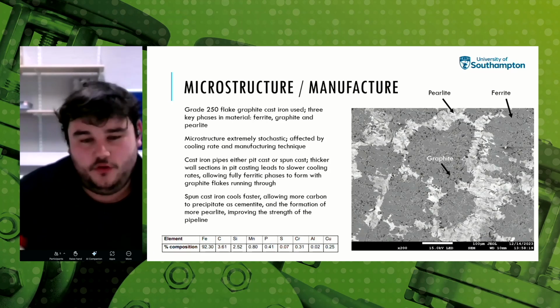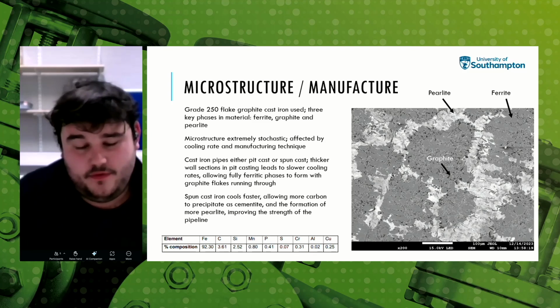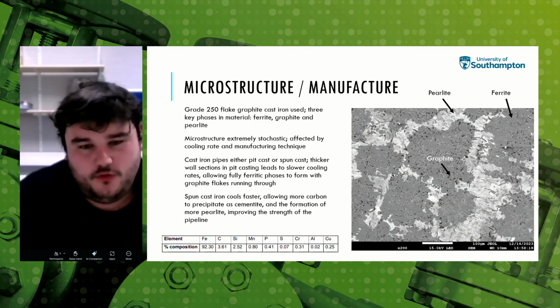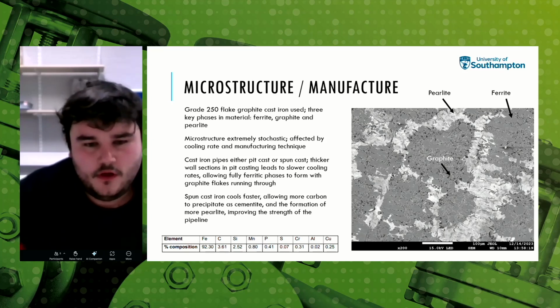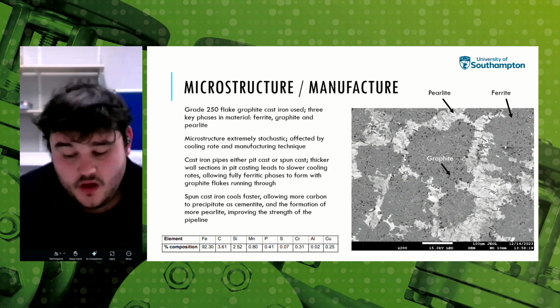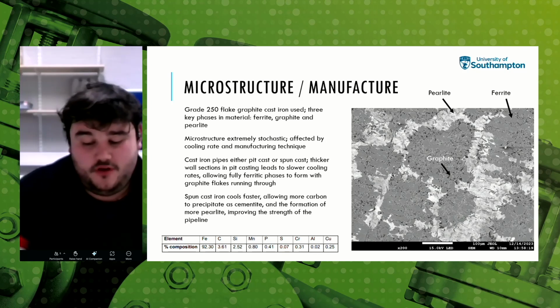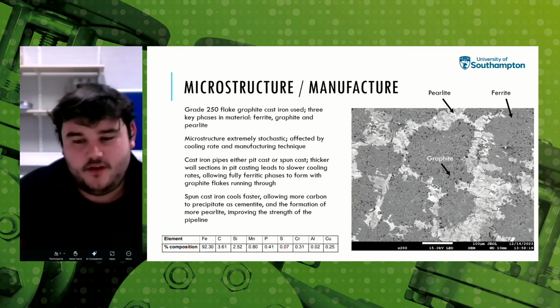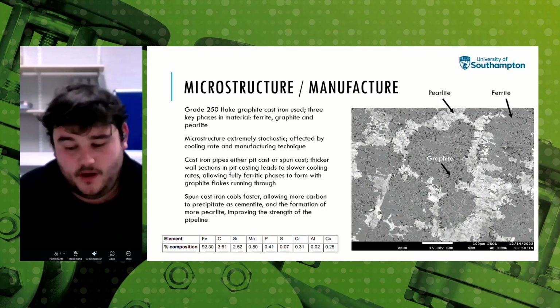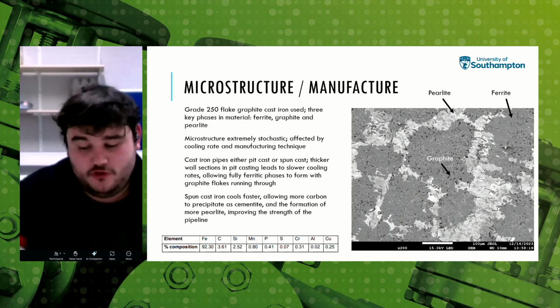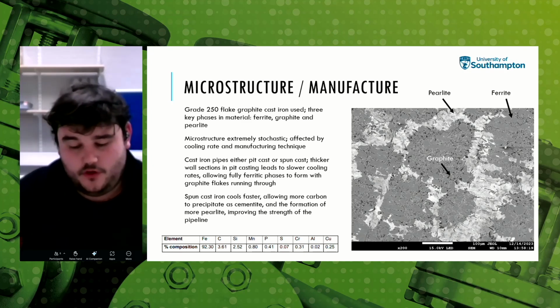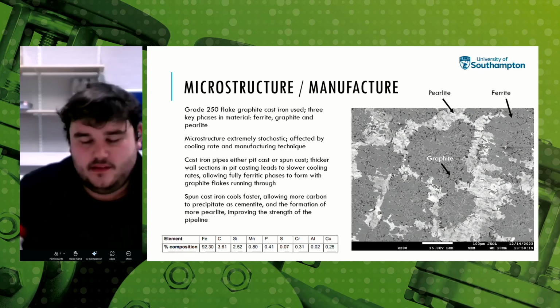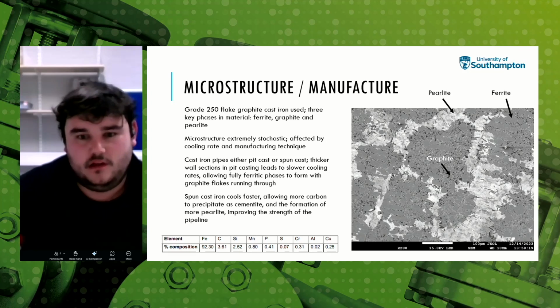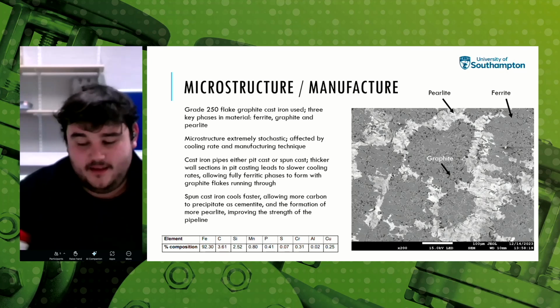As stated, this is focusing on grade 250 flake graphite cast iron, which is made of 3 key phases that you can see in the image here: pearlite, graphite, and ferrite. The dark grey regions are ferrite, the black spots are graphite flakes, and the little light grey is the pearlite. As a result of the manufacturing process, the microstructure of these materials is extremely stochastic. The size, orientation, and distribution of the phases is random by nature. The image is a scanning electron microscope image taken of an etched sample, where we use chemicals to remove the top of the surface of the material and expose the underlying microstructure, which allows us to interrogate these phases.